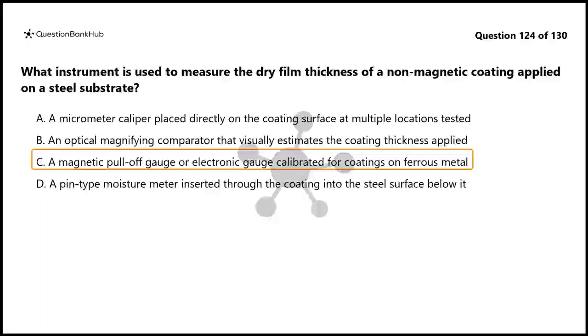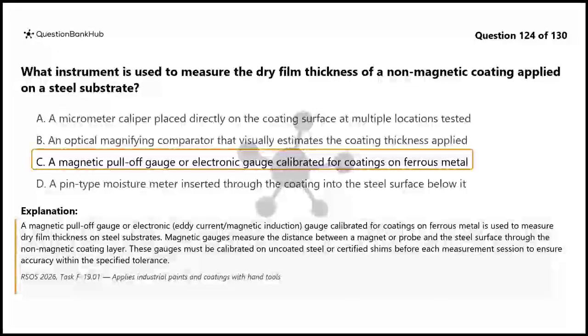The correct answer is C. A magnetic pull-off gauge or electronic, eddy current or magnetic induction, gauge calibrated for coatings on ferrous metal is used to measure dry film thickness on steel substrates. Magnetic gauges measure the distance between a magnet or probe and the steel surface through the non-magnetic coating layer. These gauges must be calibrated on uncoated steel or certified shims before each measurement session to ensure accuracy within the specified tolerance.